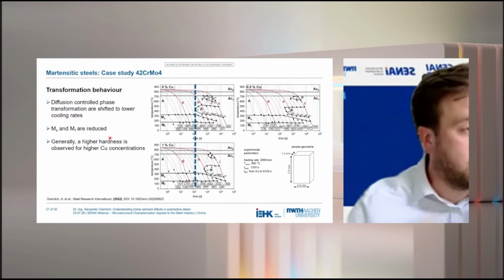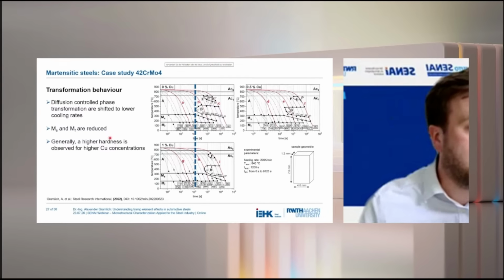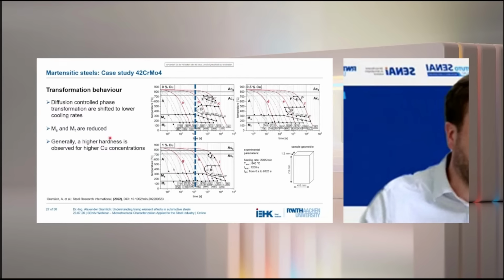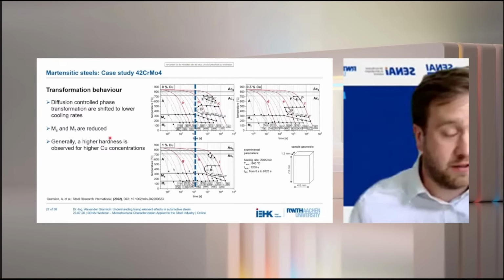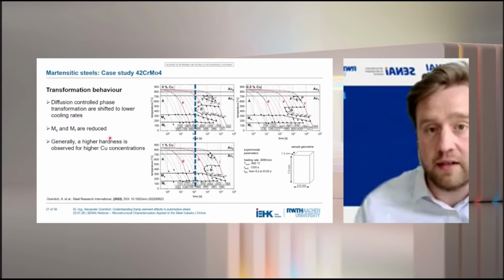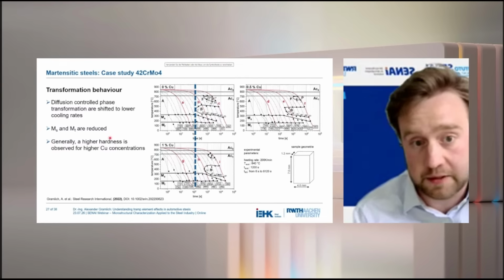However, for forging steels, this is not a bad thing, because when we increase the hardenability, theoretically, we could also produce components with larger wall thicknesses from this steel and have a complete martensitic microstructure into the core, which might not have been possible without the copper. So, in my opinion, this would be a positive effect.